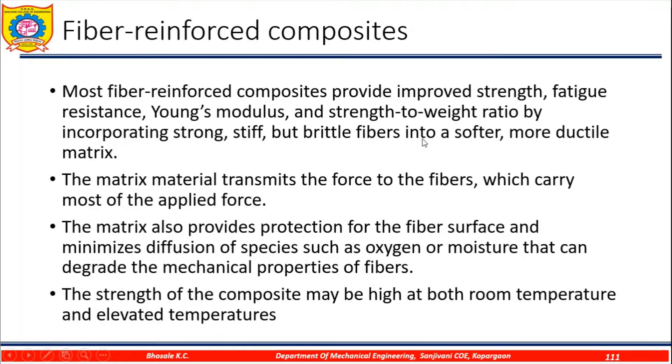Most Fiber Reinforced Composites provide improved strength, fatigue resistance, Young's modulus and strength to weight ratio by incorporating strong, stiff but brittle fibers into a softer, more ductile matrix. The matrix material transmits the force to the fibers which carry most of the applied load. The matrix also provides protection for the fiber surface and minimizes diffusion of species such as oxygen or moisture that can degrade the mechanical properties of the fibers. The strength of the composite may be high at room temperature and elevated temperatures.